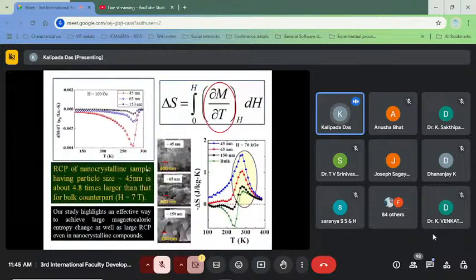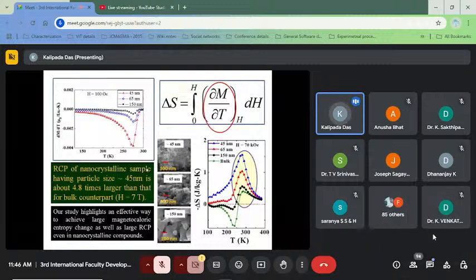Now we measure the magnetocaloric effect, and we see that in both cases, but shown here for only one sample for the sake of clarity, the magnetocaloric effect increases with reduction of the particle size. That means the 45 nanometer sample shows a large value of the magnetocaloric effect, then 65, then 150, and the bulk shows a very small magnetocaloric entropy change, and it shows the inverse magnetocaloric effect due to the antiferromagnetic ordering, obviously. So from this study, we can say that the magnetocaloric effect is enhanced with reduction of the particle size for antiferromagnetic materials.